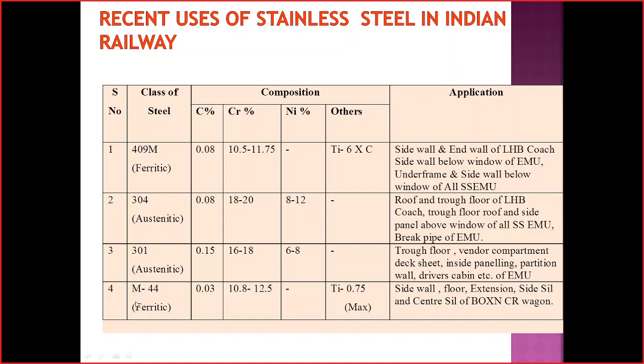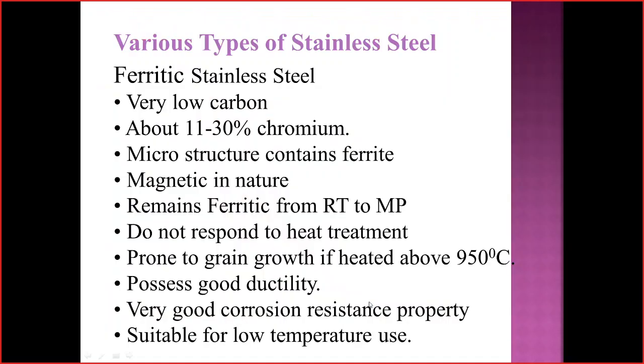This is a combination, based on which the application has been changed. Now another steel is M44, the ferritic steel. This is used at side wall, floor extension, side sill and center sill of box and CR wagon. So this is the location where we use it for wagon side. Carbon percentage is 0.03 percent. Chromium percentage is 10.8 to 12.5 percent. A little bit of titanium also, 0.75 maximum level. One by one we'll discuss.